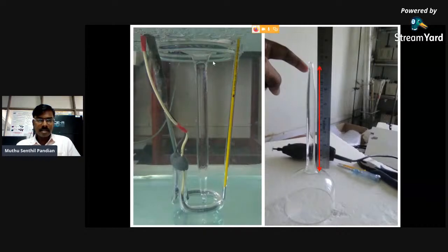Here the saturated solution is there. The temperature is around 40 degrees Celsius at the top portion, and here we have maintained 34 degrees Celsius at the bottom portion. So we have to keep it in the water bath and reduce the temperature by 0.25 degrees Celsius or 0.5 degrees Celsius per day. It depends upon the solubility of the material. We have to choose the cooling rate of the bath. So we have to wait until it reaches room temperature.